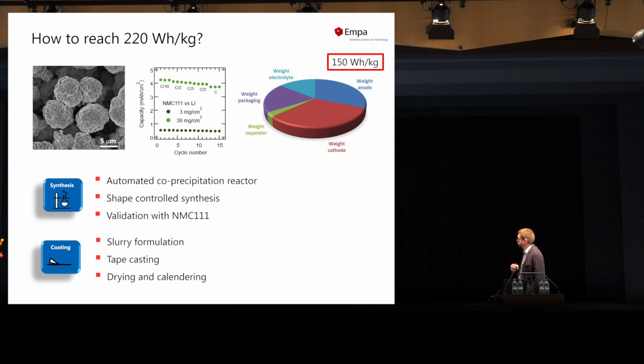Okay, so the challenge is now going from half cells, where we use lithium as a counter electrode, to graphite from Maxim Kovalenko's group. They also developed high mass loading graphite electrodes. And the problem in full cells is that the lithium you have available is coming exclusively from the cathode. So you don't have any excess lithium that you can pump into the system. If you lose this in some parasitic processes, it's lost for cycling.